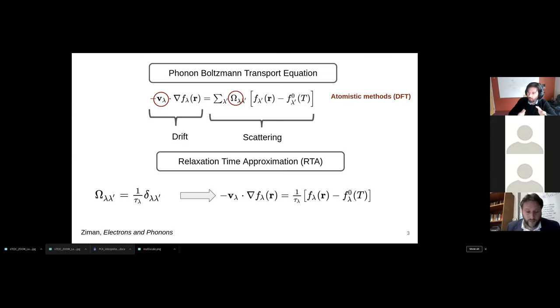This equation is a little bit complicated and convoluted. Thankfully, for most materials we can use the so-called relaxation time approximation, where we assume that the scattering operator is diagonal. And so here we have the relaxation time approximation of the BTE, in the bottom side of this slide. All right, so the goal is to model heat transport across any scale using DFT, first principle data, as an input.